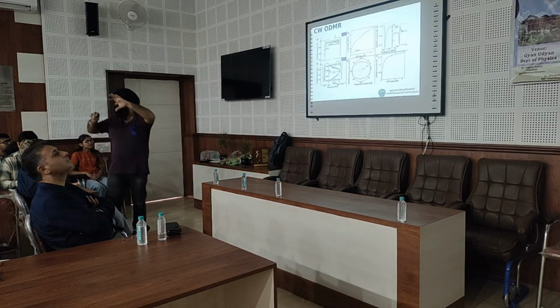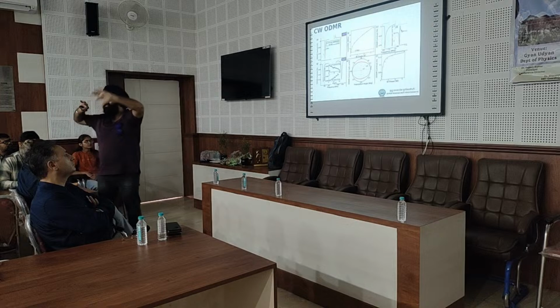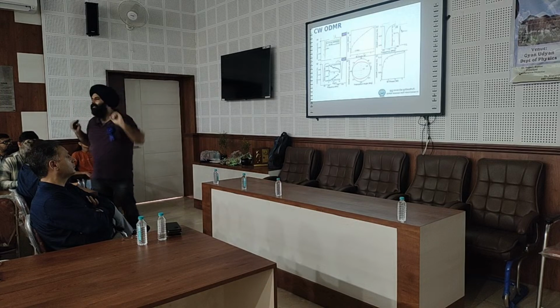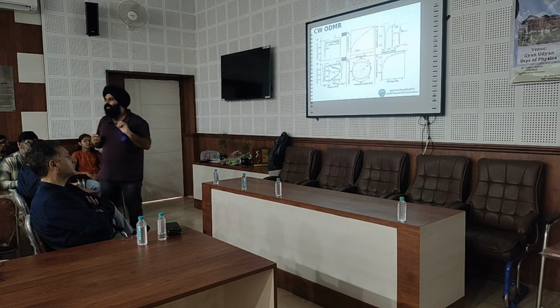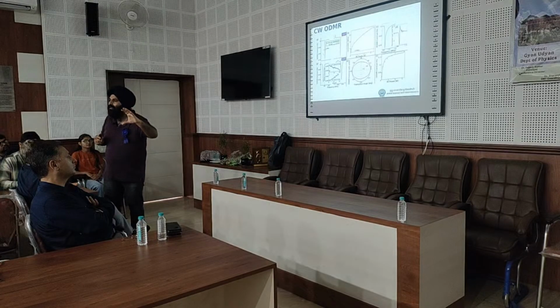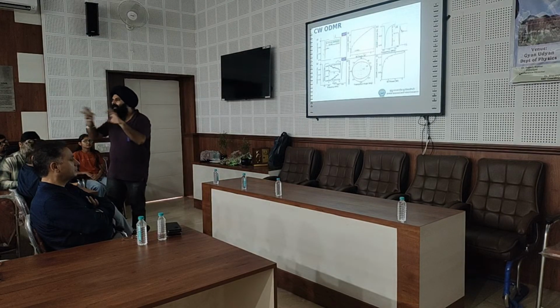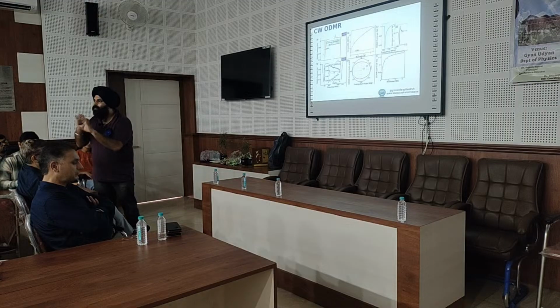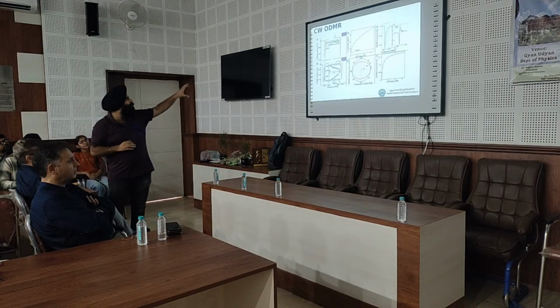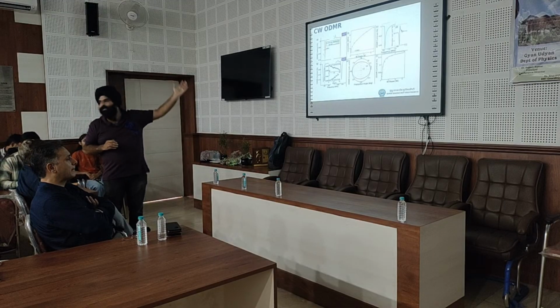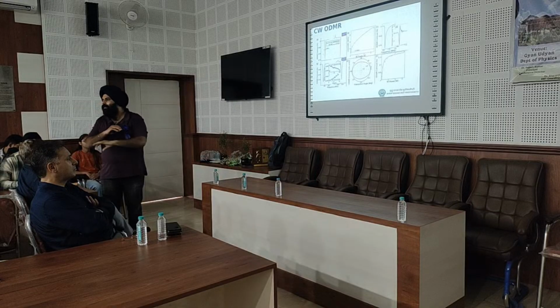Because there, the idea is that in NV we are creating the defect, and in silicon also we are creating the defect. So there is a limit. If you create a lot of defects, what will happen? You will amorphize the crystal. Okay, so if you want to create a defect in this wall, there is a limit. You cannot remove all the bricks, then there is no wall.